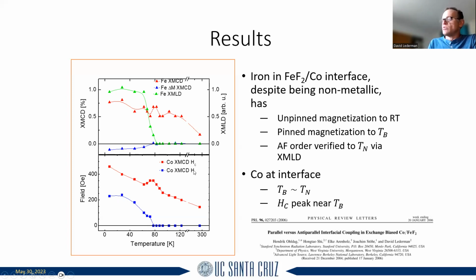Okay, and so again, this is the exchange bias measured from the circular dichroism, and this is the coercivity. And you can actually see even a peak in the coercivity. And this is something that you can actually measure just using regular magnetometry. So this was not a surprise, but it serves to prove that we were measuring the right thing. And by the way, this is the reference if you're interested in looking up this paper. Okay, this is from 2006.